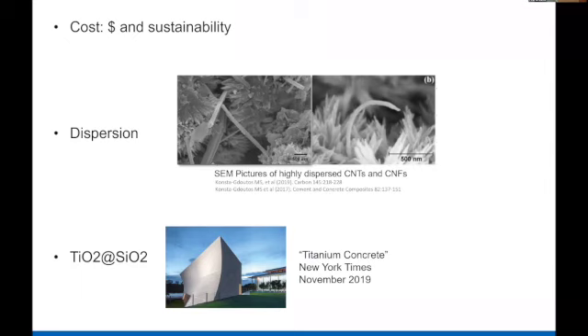So we are talking about 0.1% by weight of cement. So it's very similar to the cost of an admixture, so it could be cost effective. But the main issue is still the dispersion. We have done it in the laboratory, but scaling up is obviously a key issue. We have now started, and we have an ultrasonicator at somewhat large scale, so that we can test large scale concrete specimens.